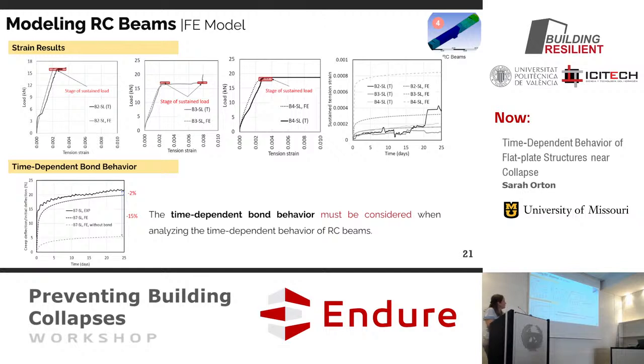One thing that I thought was interesting is we looked at this particular test where in one model we considered that bond model, and then in this model here we didn't apply the bond slip effect. And you can see a very different increase in the creep deflections with time. And so just applying that slipping of the model, at least in these beam results, was able to help us get the model results to match the experimental a lot better.